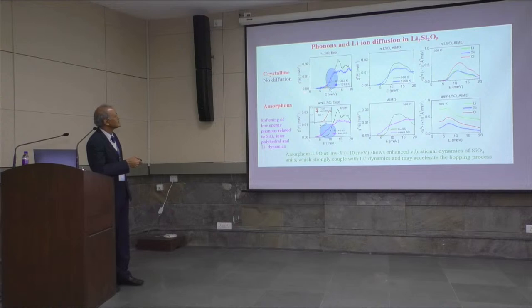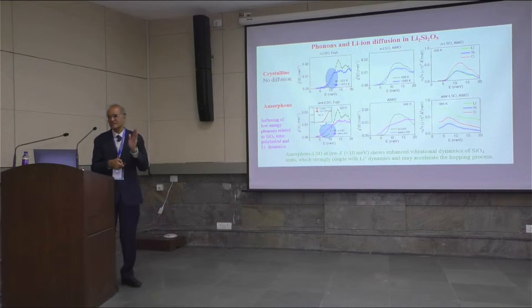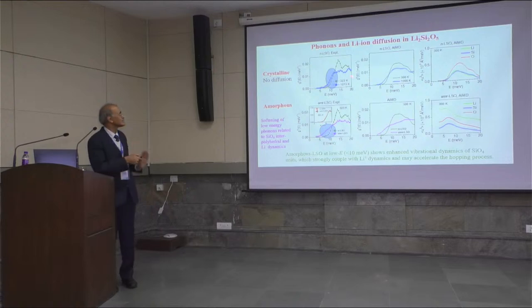Okay, so this is the phonon density of states. The neutron intensity, it's not exactly neutron intensity, but converted into the density of states as a function of energy. Normally we are familiar with the omega square kind of density of states, or E square kind of density of states. This is not just the acoustic region, some optic phonons come into play.